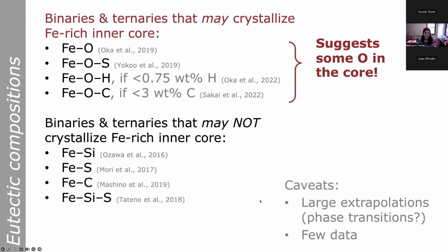But people have looked at a bunch of different binary and ternary systems to sort of ask this question of how does the eutectic composition evolve with pressure? Would the core's bulk composition be on the right side of the eutectic or not? So here's a few examples of systems where it seems like you might be on the correct side of the eutectic, although again, this often involves extrapolation. And here's some examples of a few binary and ternary systems where it seems like you'd be on the wrong side of the eutectic. They wouldn't work.